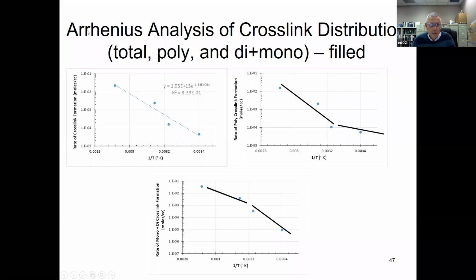Okay, so here are our crosslink distribution test results. Here is the total crosslink density. Here's the number of polysulfidic crosslinks, and then I combined the monosulfidic and disulfidic. So this is the rate of crosslink formation. This is the rate of polysulfidic crosslink formation, and here's the rate of mono and di crosslink formation. And it's plotted on an Arrhenius plot, and we see no evidence of a mechanism change.